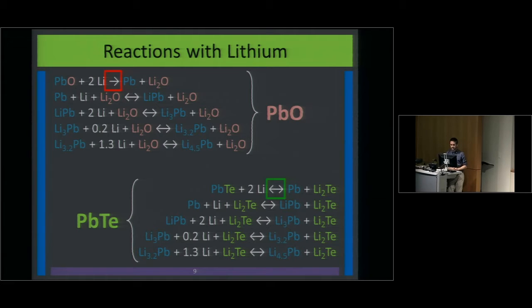The main reason for this is the difference in electronegativities between the two. It's a pretty high difference for lithium and oxygen, but it's lower for lithium and tellurium, so you're able to separate those two.